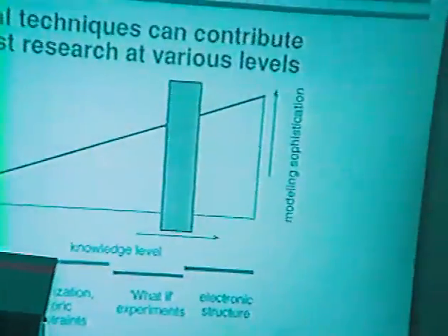This category is what we call what-if experiments. What happens if I change the silicon-to-aluminum ratio in a zeolite, which you often do in experimental work? Where are my reactive sites in my zeolite? You can calculate that with these kinds of experiments, because you can do a sort of simulation, and I will talk a little more about that later on. You can create defects in your structure and calculate defect energies, or calculate what additional reactive sites you get if you replace the silicon by titanium.